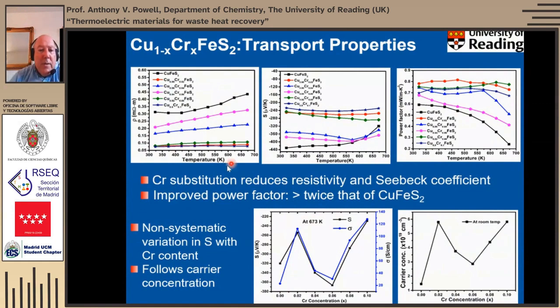However, the fly in the ointment is that we find if we take the Seebeck and resistivity at a given temperature, and we're choosing 673 here, we see that they vary in a non-systematic way with chromium content. We might have expected them to vary steadily as we increase the amount of chromium, but instead of that, they follow this sort of double zigzag type curve, and that mirrors the carrier concentration, or the changes in carrier concentration.